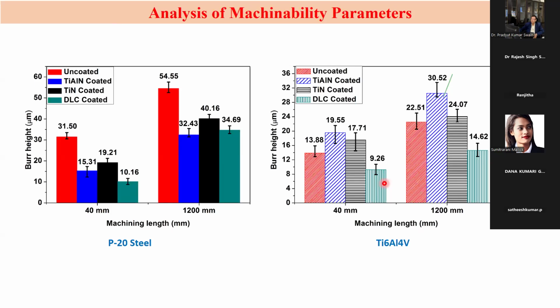However, for machining of Ti6Al4V, the TiAlN and TiN could not exhibit better performance compared to the uncoated and DLC coated tools.